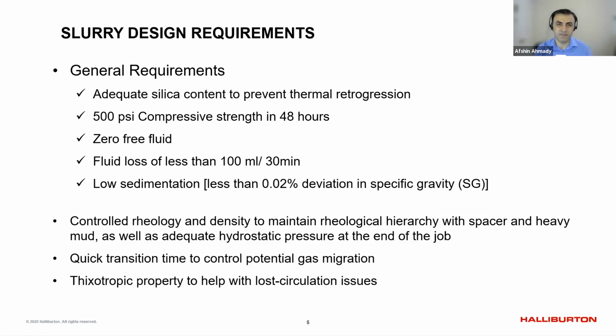These are the slurry design requirements. This is pretty much common for all the production jobs. Zero free fluid for the lateral section, that is for sure, and 500 psi compressive strength within 48 hours. This is the minimum requirement, and silica flour is required to prevent thermal retrogression over time for high temperature design. And fluid loss needs to be less than 100 cc per 30 minutes. That's the unit they are using for measuring the fluid loss. And sedimentation is the biggest part of this. To me, it is the most reliable variable you can look at when you have any concern with losing the properties of a cement.